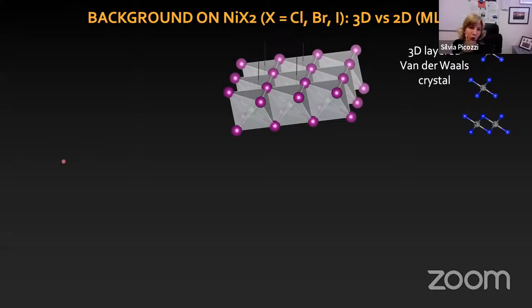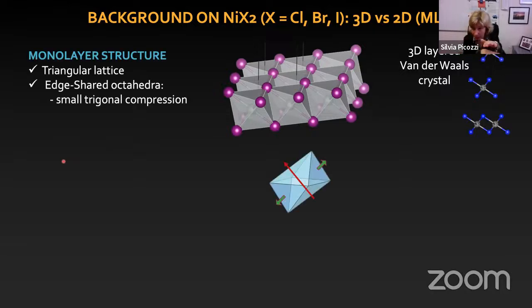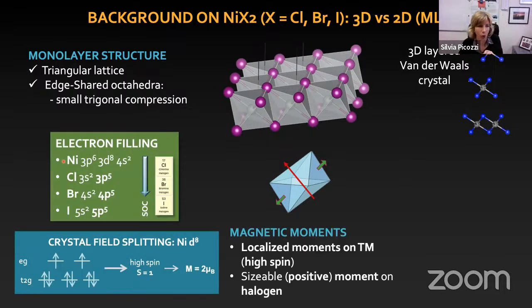Yeah, so mainly the talk will be on nickel halide. So I wanted to introduce a bit the system. They exist in crystalline form. They are van der Waals crystals. And if I slice one monolayer, I basically see that the arrangement of nickel is on a triangular lattice, and every nickel is surrounded by a cage of octahedral halide, and they are edge sharing. There is a small trigonal compression in the direction perpendicular to the layer, but that's really small.